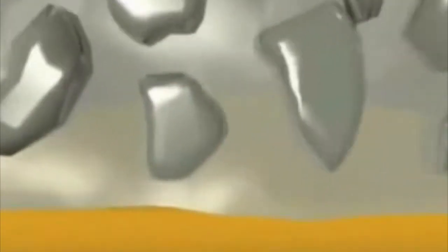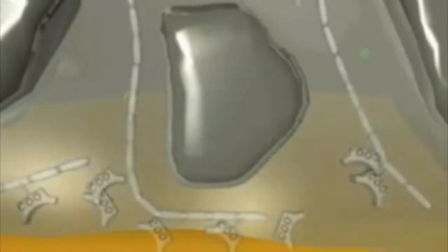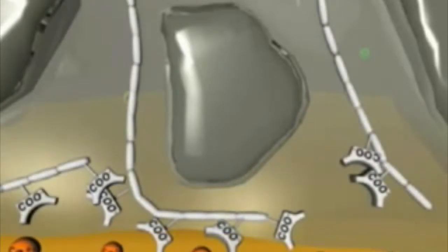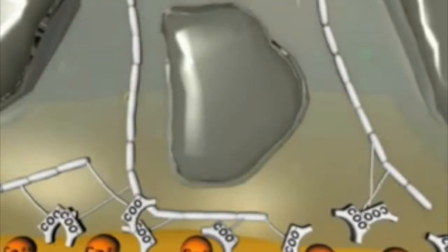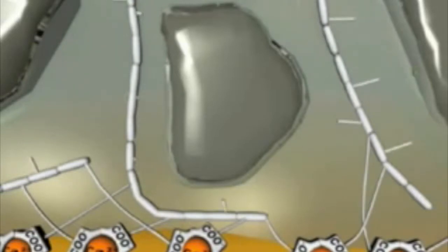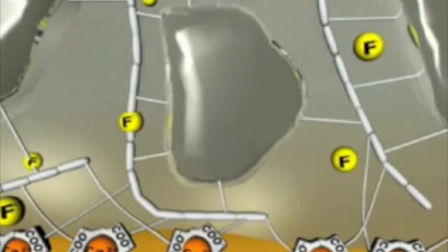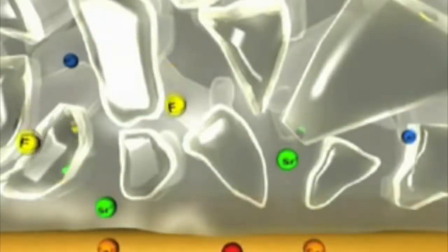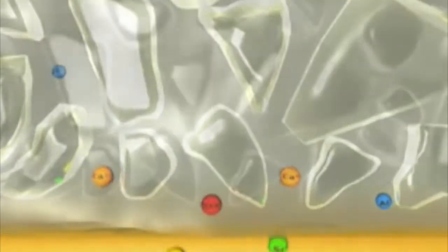It is essential that the glass ionomer is placed while it has a glossy surface. The gloss is free polyacid, which is able to penetrate the cavity surfaces to form a strong, hydrolytically stable chemical bond to calcium ions within the dentin and enamel. In addition to chemical adhesion to calcium in the tooth, a micromechanical bonding process takes place as well.